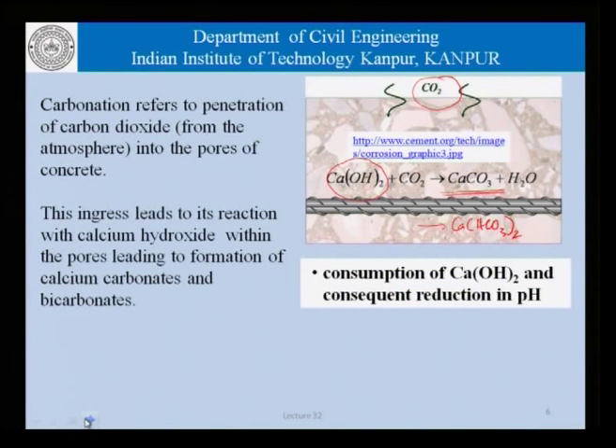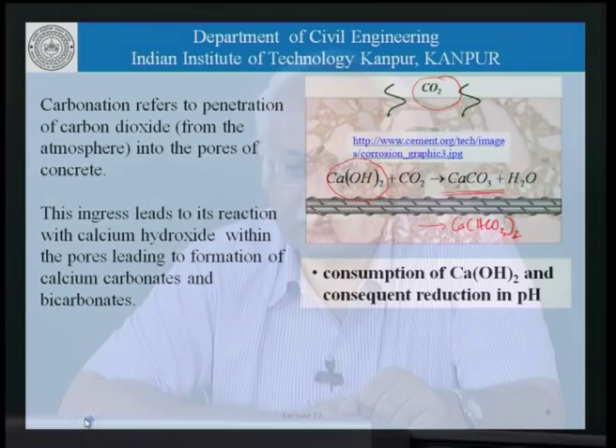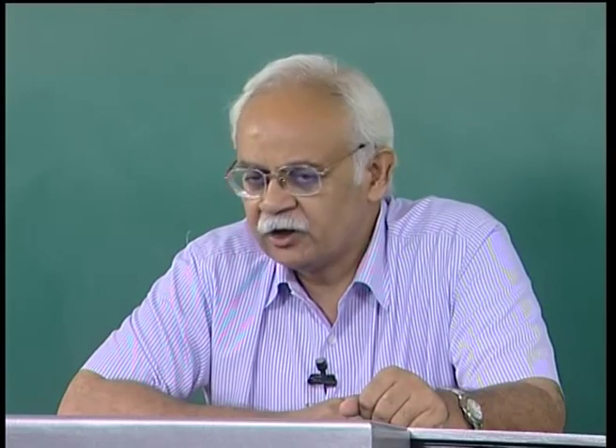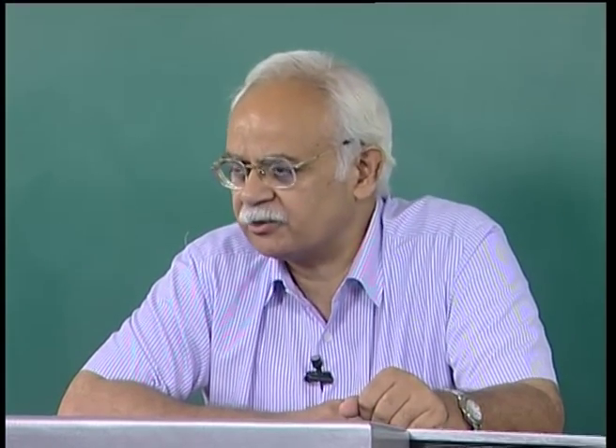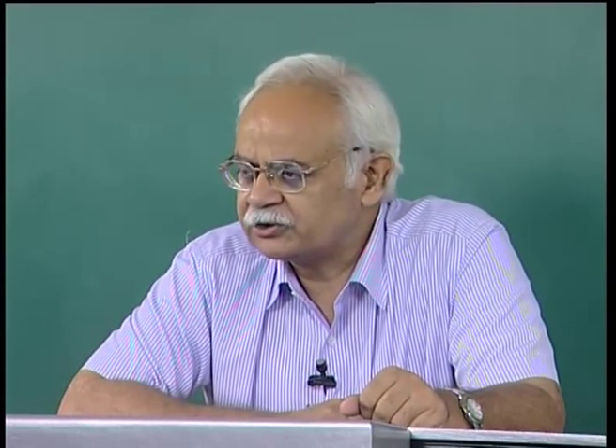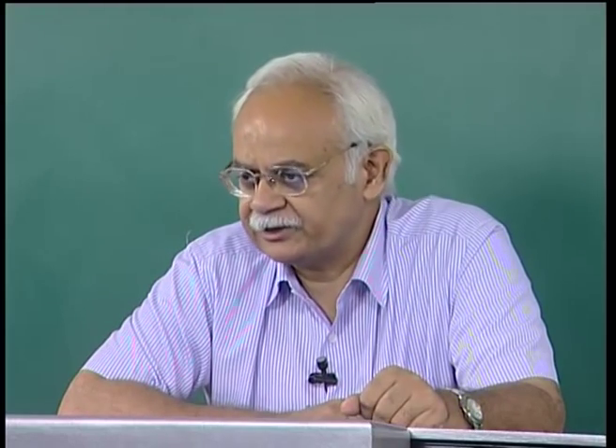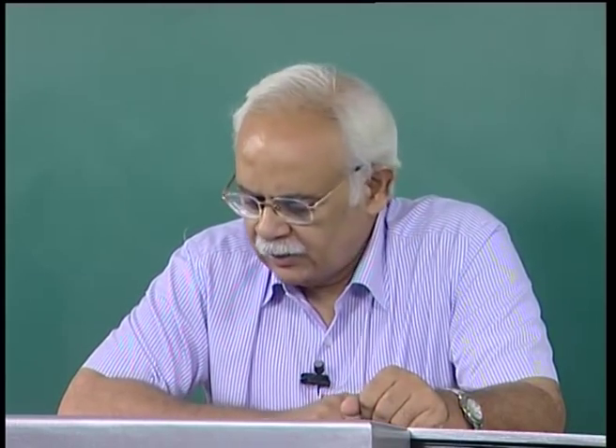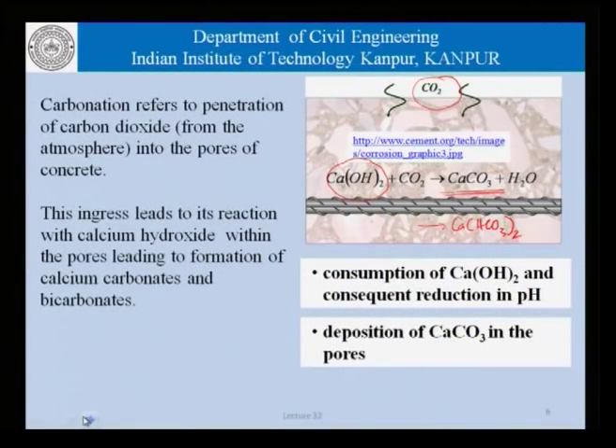So, in principle, what happens as a result of the carbon dioxide ingress is the consumption of calcium hydroxide and the consequent reduction in pH of the pore solution. So, this calcium hydroxide is responsible for the very high pH, which is in excess of about say 12 or 13 in the pore solution. Now, naturally, if calcium hydroxide gets consumed and converted into calcium carbonates or bicarbonates, the pH of the pore solution will go down. So, this reduction in the pH has its own implications as far as the durability is concerned, as we shall see shortly. And we have the second part of it, which is deposition of calcium carbonate in the pores. So, this deposition of calcium carbonate in the pores has its own implications in terms of the properties of the concrete.